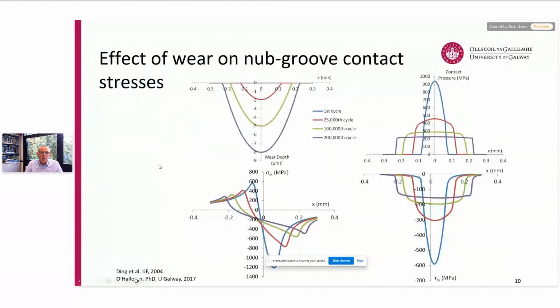And then you might ask yourself, well, why should we bother caring about wear? Is it important? And I would say, yes, I think it can be exceedingly important. In this particular case, I'm showing some examples which show perhaps pretty extreme wear, but actually about 8 microns worth of wear in the top left after about 200,000 cycles. And then in the top right, you can see how the Hertzian contact pressure reduces as a result of that, and the contact scar widens, as Phil showed examples of experimentally, and you get a much reduced pressure, a much more uniform pressure. And then, of course, what that leads to is changing, evolving sigma xx and tau xy stress distributions across the contact region. And in this particular case, if it's a gross slip case, as it is here, then the stresses actually reduce. So that would mean if you didn't take account of this, you would typically be overly conservative, for example.